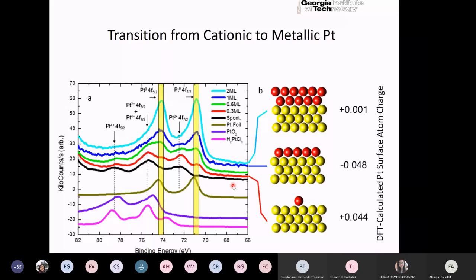What about the stability? When we have the graphene as a sandwich, it increases our platinum retention quite noticeably. You can see that when you have 3 monolayers of platinum on graphene and more than 3 or more layers, we essentially, after 1,000 cycles, retain about 70% of our catalyst. Whereas same 3 monolayers without the graphene, we lose nearly 50% of our catalyst. So that's just one case.